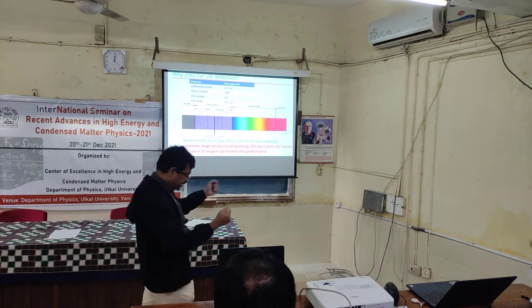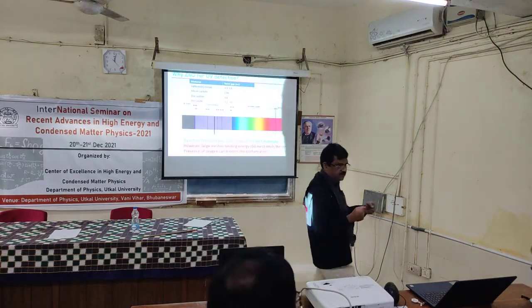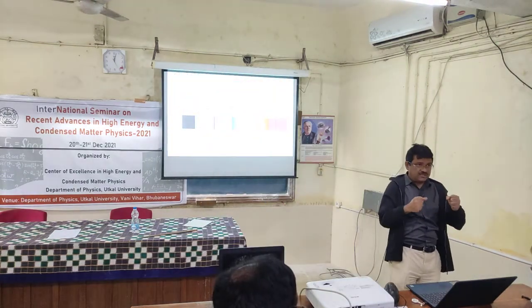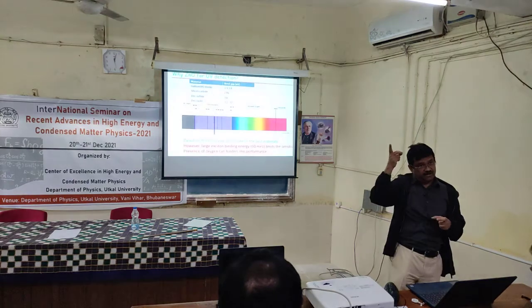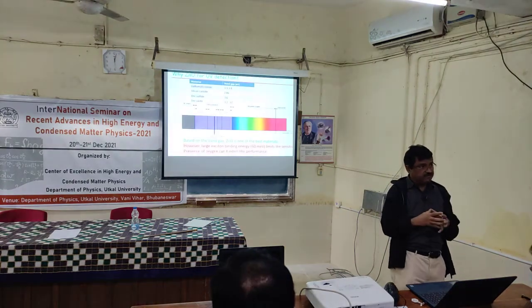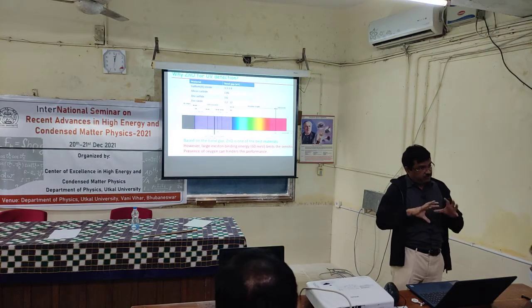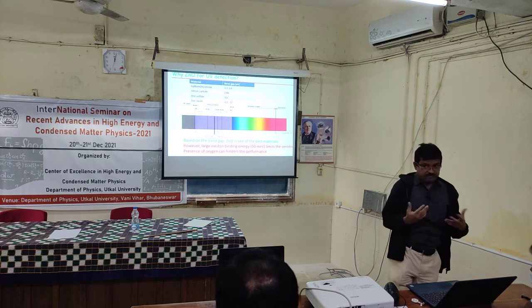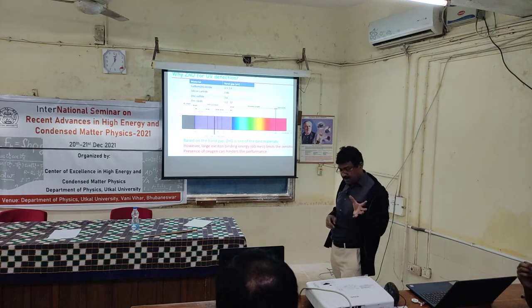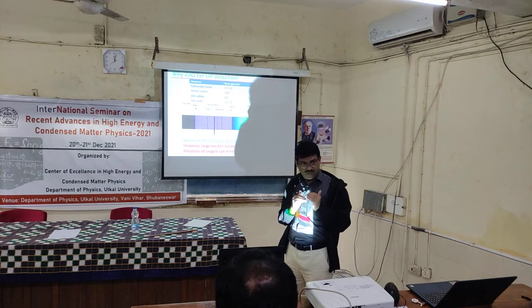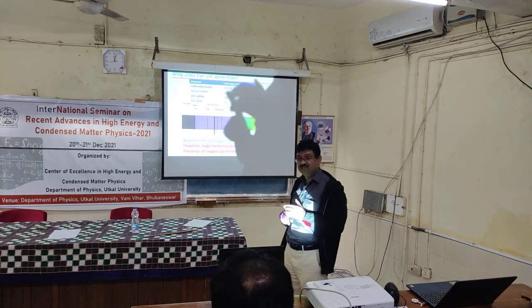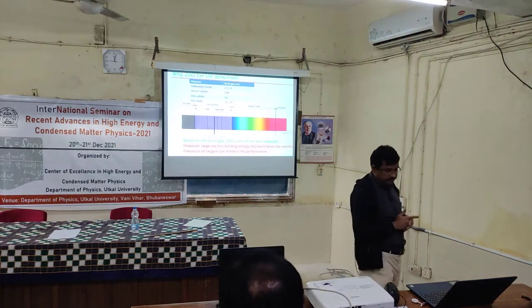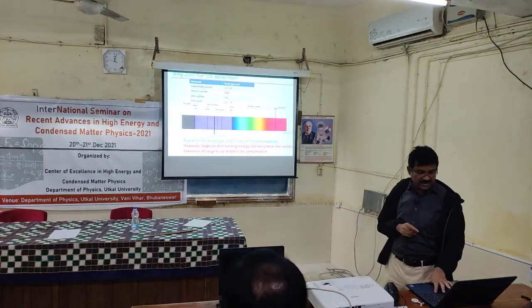So you can separate them. But once they see each other, there is a good chance that in zinc oxide they will recombine much faster, because the binding energy between them is 60 meV, which is higher than room temperature. In gallium nitride, it is 25 meV, which is close to room temperature. So the chance of recombination in zinc oxide is much higher. So how can we handle this?